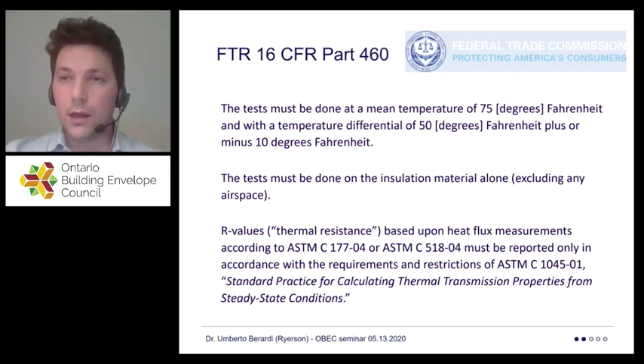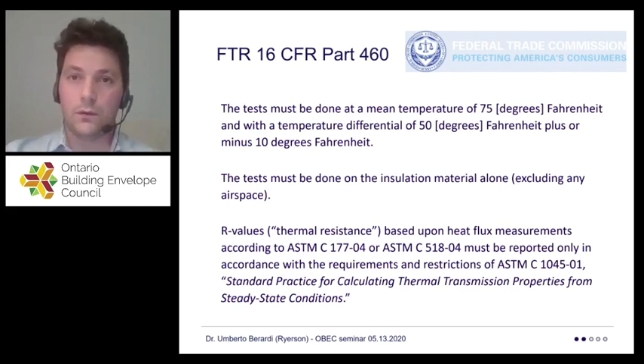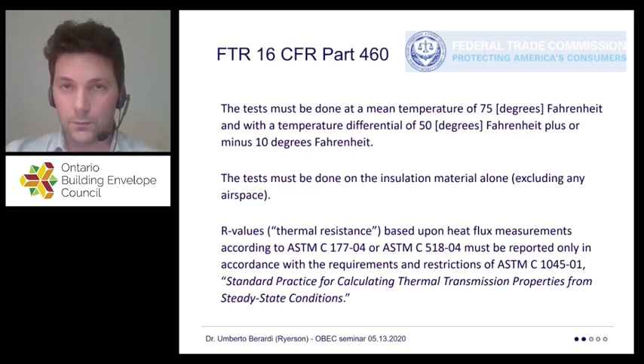So in the middle of the material, you need to have 75 Fahrenheit, and you need to have basically 50 Fahrenheit on one side, the cold side, and 100 Fahrenheit on the warm side. So cold side at 50 Fahrenheit, warm side at 100, 75 in the middle, and we try to establish in a lab a kind of homogeneous heat flux, unidirectional, across the material that is exposed to this 50-degree Fahrenheit difference.